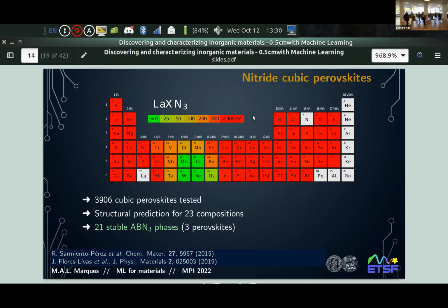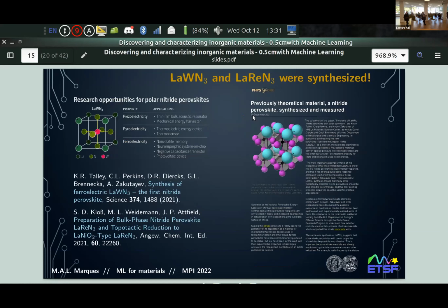Okay. Now, this was in 2015. We published this paper. I asked a few experimentalists around, they all told me it was very hard. But to my surprise, last year, 2 of these 3 predictions were actually synthesized. The first one was lanthanum tungsten nitride, a Science paper from an American group, and also lanthanum rhenium nitride was synthesized. And we were actually very happy that we also got the prediction of the crystal structure correct.